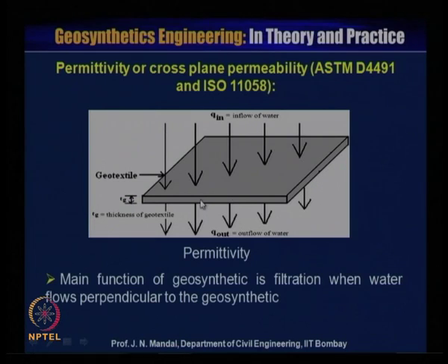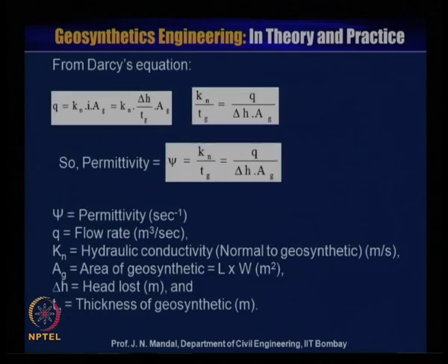The main function of geosynthetics is filtration when the water flows perpendicular to the geosynthetic material. Now, what is the theory? From Darcy's equation we know Q is equal to Kn into i into Ag, and i is delta H by Tg.